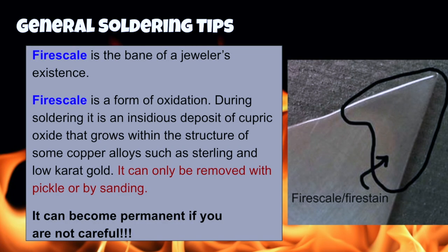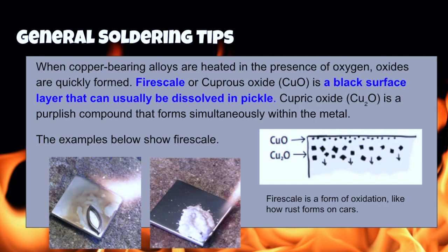Fire scale is really the bane of the jeweler's existence when soldering or finishing work. Fire scale is a form of oxidation, like rust, that can be removed with acid that is in the pickle pot. You have to be careful as it can become permanent if you overheat your piece an extreme amount. A couple of other tips to avoid fire scale are using a hit and run technique, meaning that you keep the flame moving in concentric circles to avoid heating the metal too long in any given area.